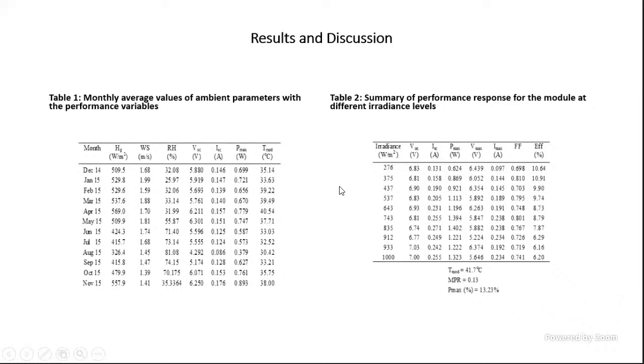And then from table 2, we can also see that efficiency peaks at lower irradiance, in this table at 375 watts per meter squared. And then when the irradiance starts going higher, and that means higher temperature also, the efficiency starts going down. So sunlight and the heat is not everything.